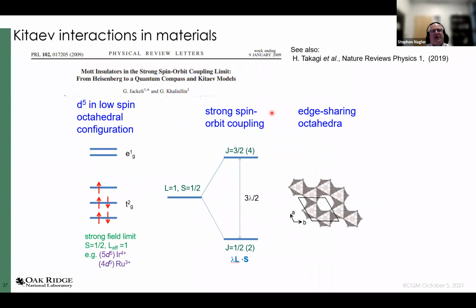So this is really the paper that I would say started a lot of activity in the field. It was a realization by George Jackeli and Giniyat Khaliullin that you could have Kitaev type interactions in materials under the following circumstance. So we think about this D5 system that I already mentioned in a low spin octahedral configuration. They were initially considering, strictly speaking, iridates. So we're in the strong crystal field limit. And one thing to note is that the largest perturbing energy in the system actually is the cubic crystal field. The next largest energy is strong spin orbit coupling, and that gives me a J equals a half ground state.